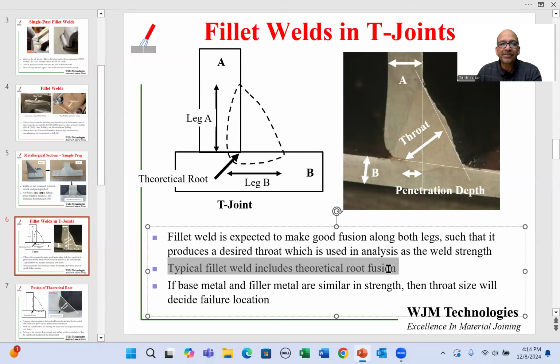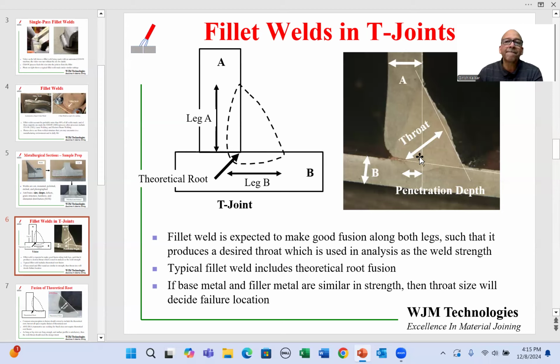Typical fillet welds include root fusion. So when you say we have made a fillet weld, typically one would expect that the theoretical root has been fused. What that means is the fusion in the fillet weld has extended at least up to the theoretical root and a little bit beyond. And that beyond, along the weld interface, is measured as the penetration depth. So the distance from the theoretical root to the actual root is the penetration depth.